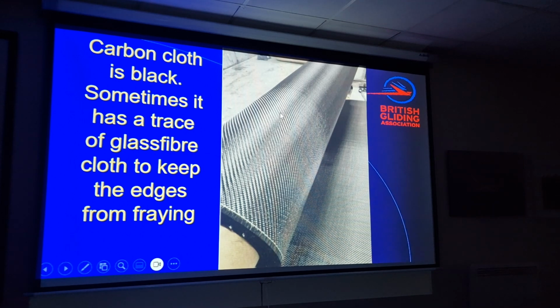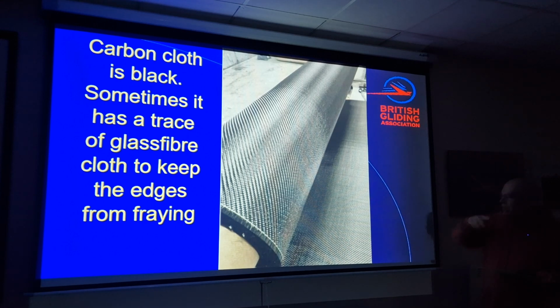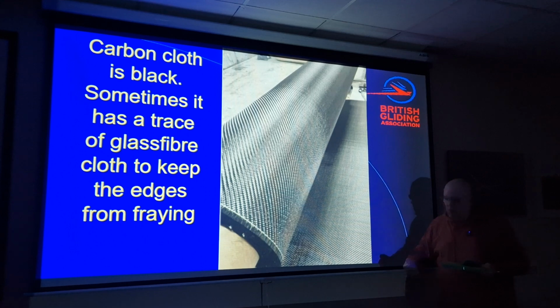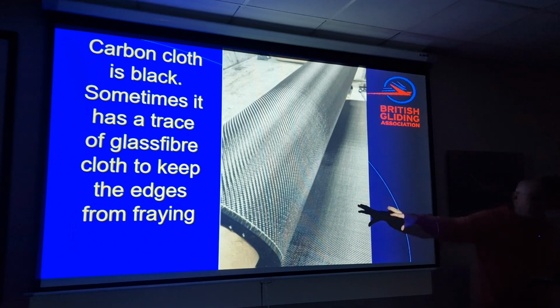This is carbon fibre, and it comes on a roll. You're not allowed to fold it. It will snap. Very brittle material, quite easy to work. When you're laying it up, you generally use rollers and brushes on it, because if you put a hard metal scraper on it, you can quite easily just break all the fibres.